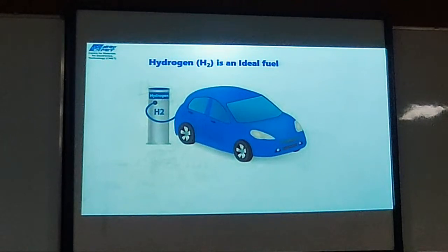What we can do, we can have very highly porous solids. In the highly porous solids, we can press the hydrogen. This hydrogen is covalently bonded with this material, and at low temperature, just giving 50 degree temperature, that can release the hydrogen. So whenever we require hydrogen, we can do that. So this can be useful for two-wheelers. Then it can be useful also for electronic systems and all these things.